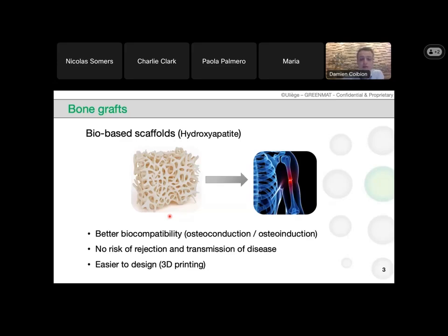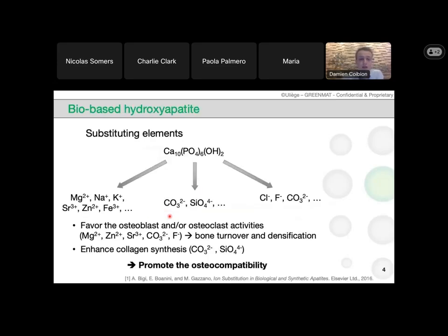So what are the advantages of the biogenic hydroxyapatite compared to a synthetic hydroxyapatite? It's mainly the substituent elements found in the natural hydroxyapatite. Each site of the unit cell can be replaced by different elements. Mainly the calcium can be replaced by other cations, such as magnesium, sodium, potassium, and so on. The phosphates and hydroxide groups can also be replaced by carbonates, silicates, chlorides, and so on. And it is known that these elements are involved in the osteocompatibility of the graft.